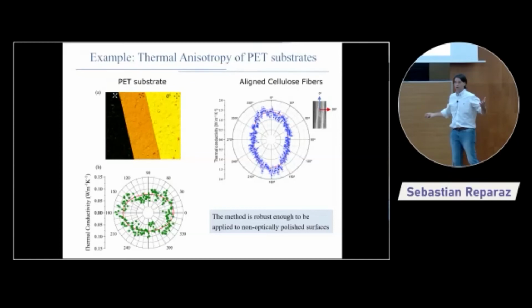And of course, the result is a little obvious, but measuring this is not so simple. And that is in the direction of the fibers. You have a thermal conductivity that can be twice as large, or 1.8, 1.7, as compared to the perpendicular direction when you have very poor coupling, at least from the thermal point of view.